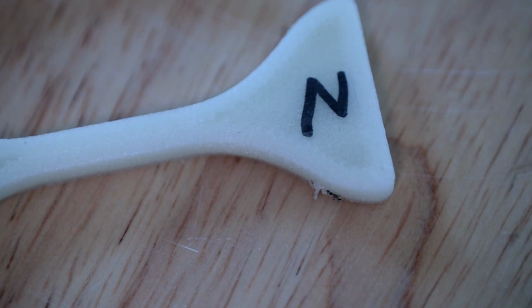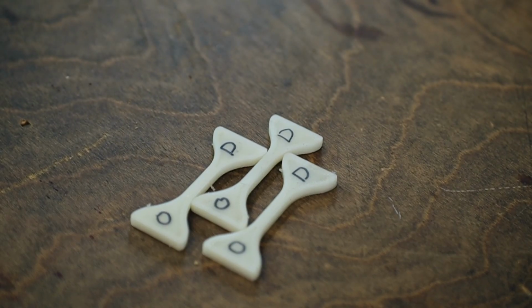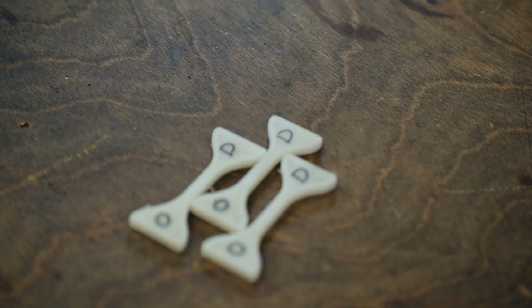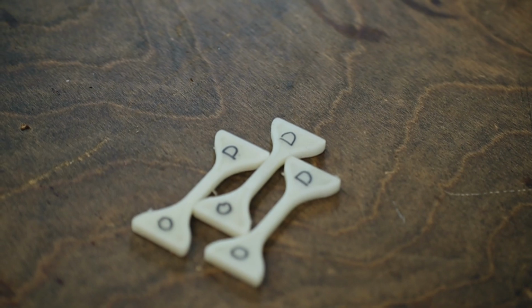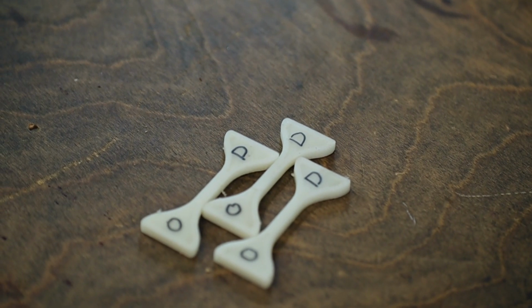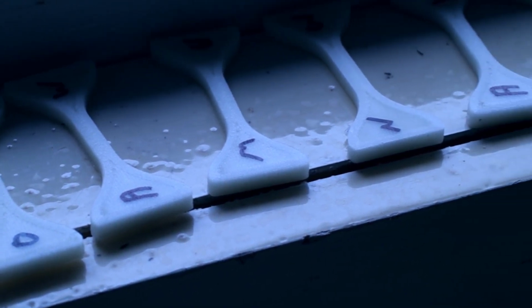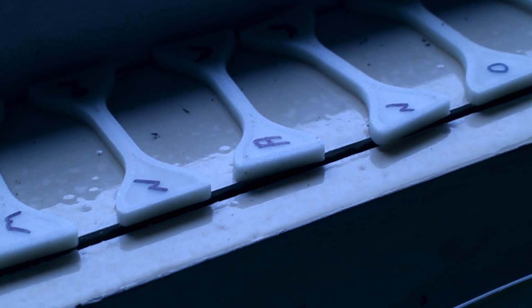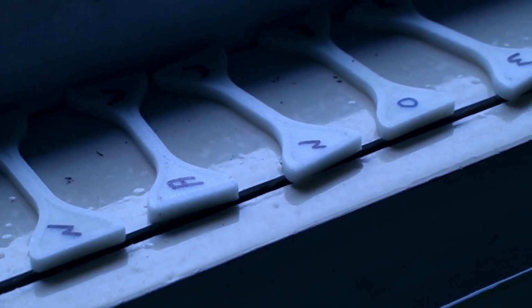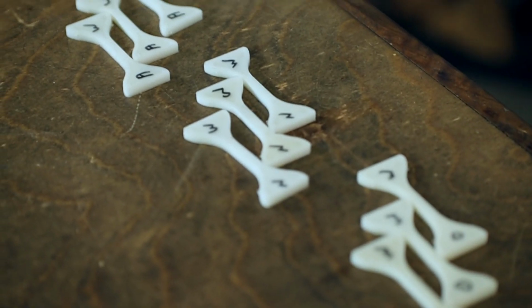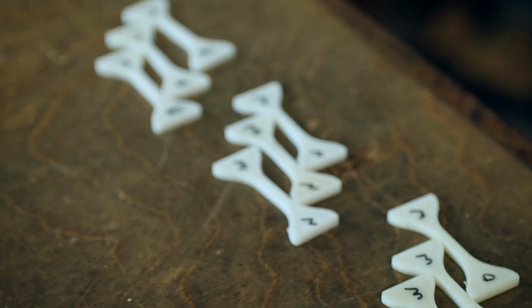I then took my samples, which are now all back in the dry box, and I took each of these sets of 6 and split them into 2. So I now have sets of 3. Half of these samples I left in the dry box. The other half I placed on my windowsill for 2 weeks at ambient conditions to absorb humidity. And here in Tennessee, the humidity is quite high this time of year, probably over 70 to 80%. So this is, I think, a realistic test of what a real-world part would be exposed to in the atmosphere.